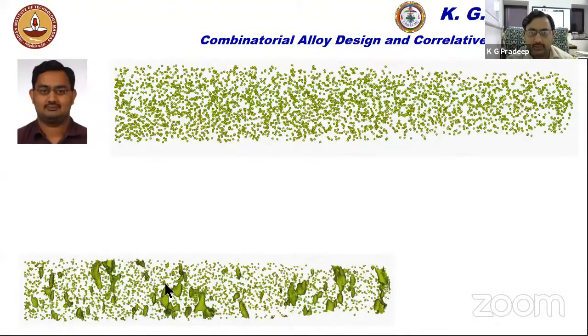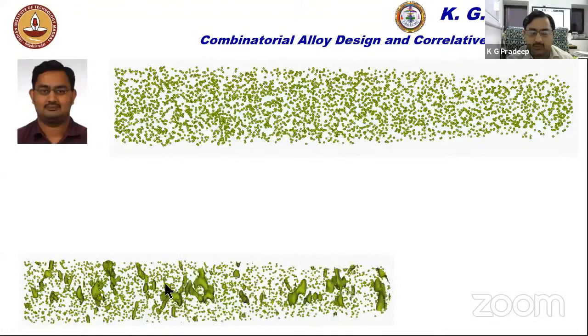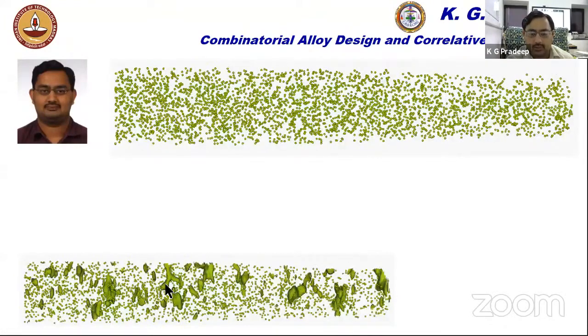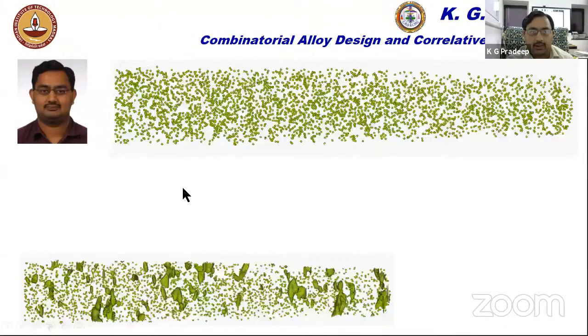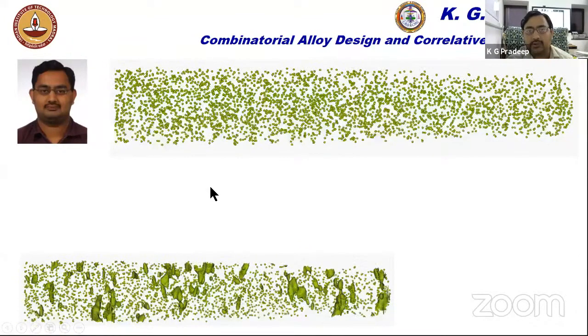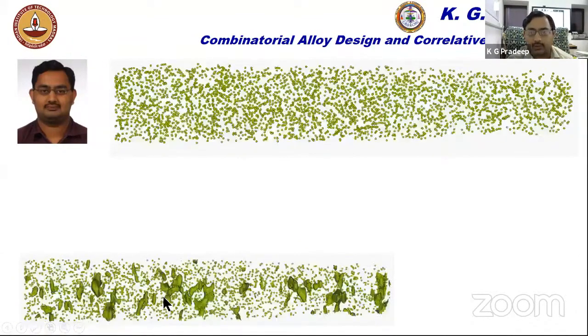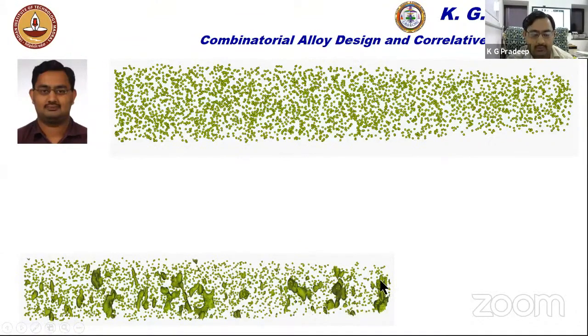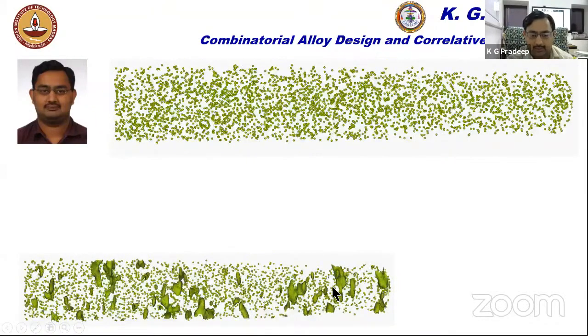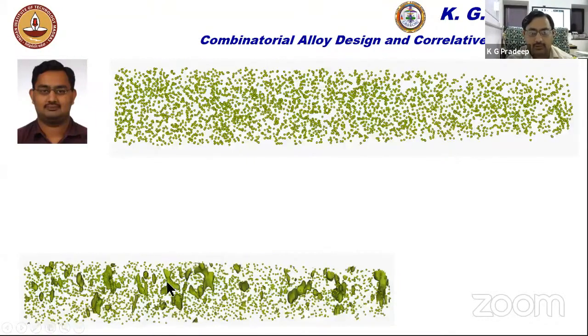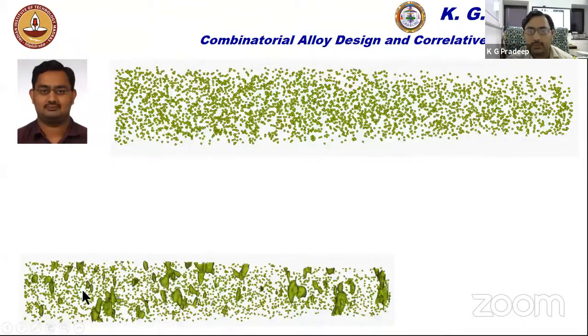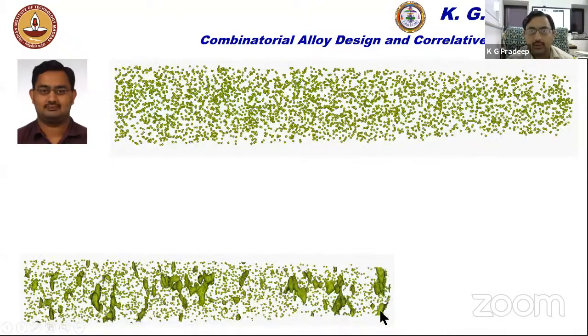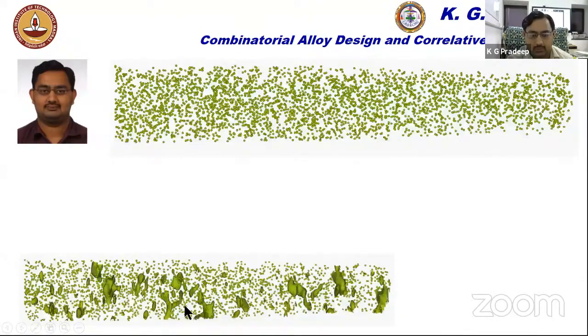Now within this region, we are able to identify, with a certain concentration threshold, an accumulation of nitrogen atoms in localized pockets, which are these defect sites enriched with stacking faults and dislocations. So you can now see there are a lot of these nitrogen atoms being clustered in a local region, which is all happening because of the presence of defects, as we saw in the electron microscope image. So what more can we do with this?